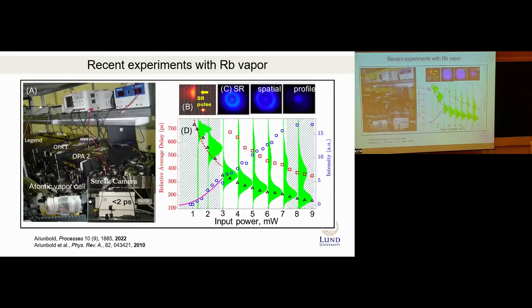Here are more recent experiments with rubidium vapor. This is a confusing plot, but basically, in this paper, the researchers show the experimental setup, so sort of what it takes to get it in the atomic vapor, some pictures of the superfluorescence, and then the superfluorescent pulse as a function of excitation power. At a weak excitation power, there is a large delay. This is this red axis. That's why it's a weird plot. At a high excitation power, n is much larger, and superfluorescence happens faster and shows this oscillation.